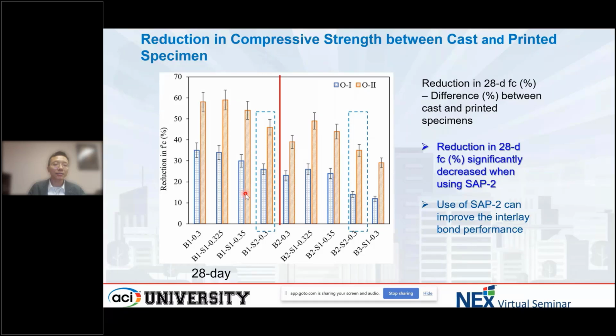As we add the SAP2 to the mixture, compared to the reference, the reduction of the compressive strength between the cast and printed specimens decreases a lot. This is another advantage of using SAP2. It improves the surface quality, it also improves the bond performance, and then it increases the compressive strength of the printed filament.